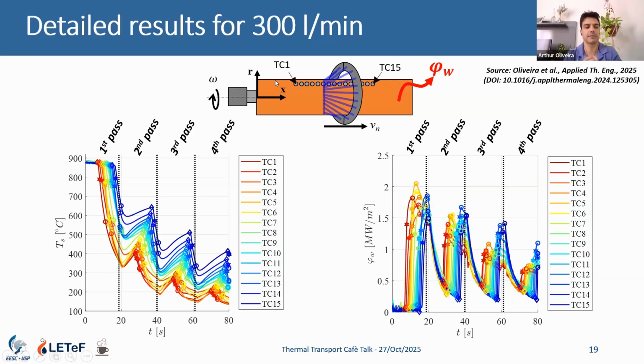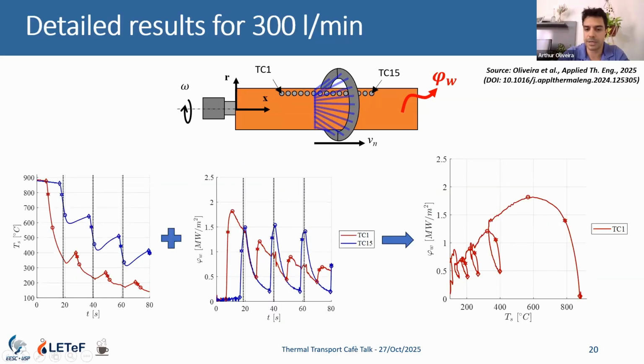For us to compare the results, the temperature evolution, heat flux evolution over time means very little. So you normally want to plot this as a boiling curve, heat flux over surface temperature. Let's say for one thermocouple, you have the onset of cooling, maximum cooling rate point, maximum heat flux, then the cooling process, the end of the first pass, the decay in the heat flux, and this loop profile of the boiling curve.